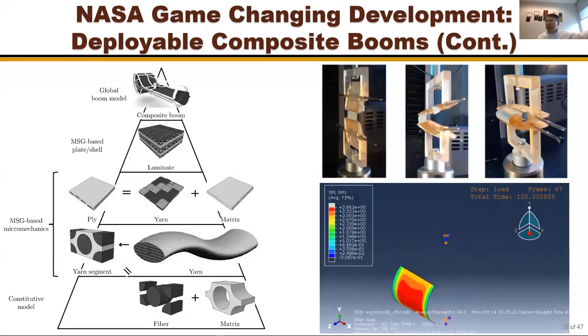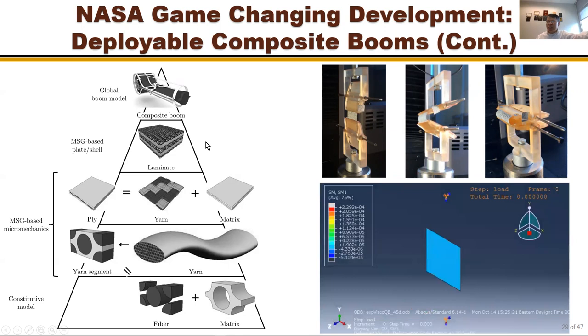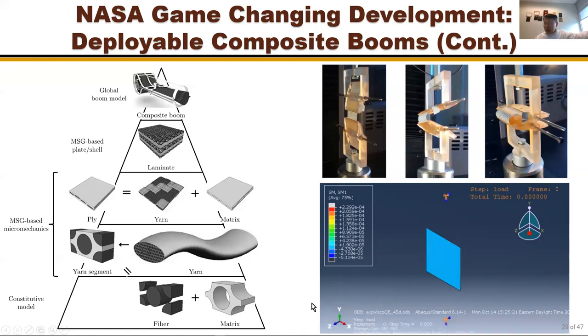All this can be predicted and analyzed using our method because when deployed the boom is a beam, and when packed it's a shell — both made of woven composite. For simulation, for each yarn there is fiber and matrix; you make the yarn, then the woven fabric, lay up together to make the boom. We simulate column bending tests in Abaqus, calculate equivalent viscoelastic plate properties in terms of fiber/matrix properties, implement that as a UMAT for Abaqus, and then Abaqus performs the nonlinear simulation.